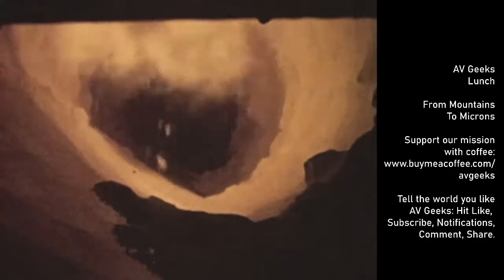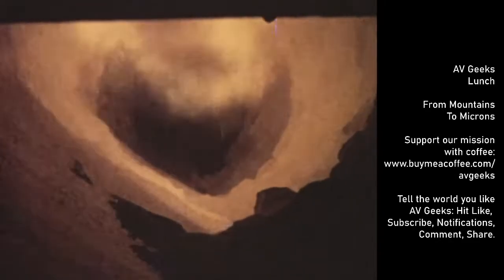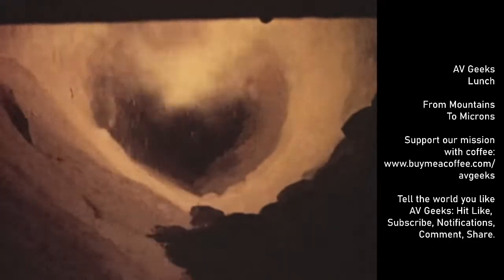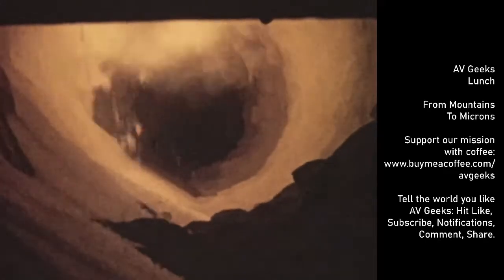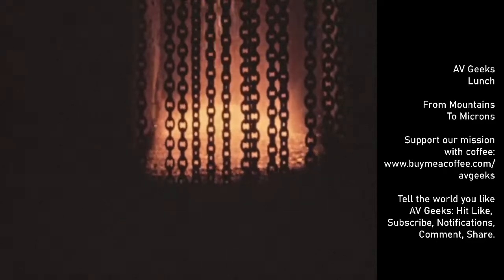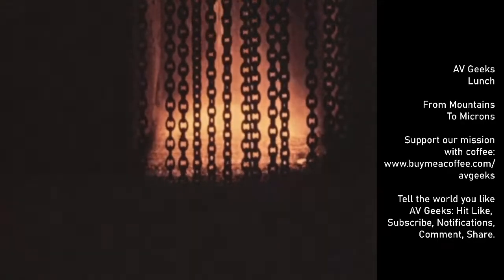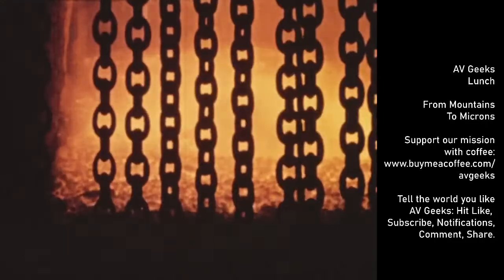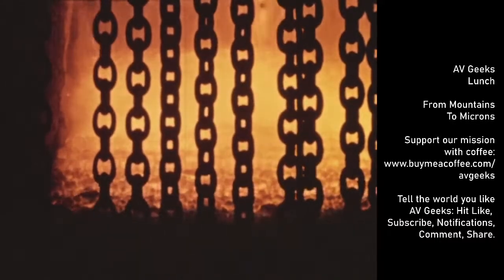During heating, the materials pass through a spectacular range of color changes from glowing violet to red to white-hot incandescence. Here is where the chemical transformation of raw materials into new, useful compounds takes place. During the 4 hours required to pass through the kiln, the calcium silicates, aluminates, and other compounds are formed that give Portland cement its binding ability and strength. When the heated material emerges from the end of the kiln, it appears in the form of red-hot, marble-sized, glass-hard balls called clinker.